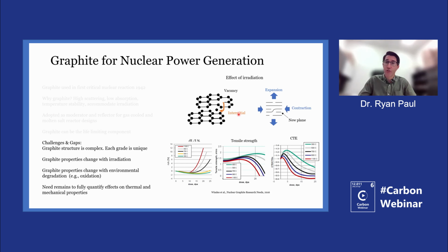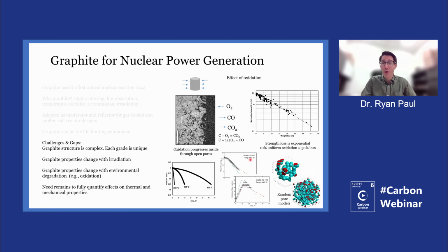So all these changes to the graphite structure result in changes to the volume, changes to the tensile strength, changes to the thermal expansion coefficient, which are very irradiation dose and temperature dependent. And so depending on the design envelope of the reactor particulars, all of these need to be incorporated into the integrity understanding, just from the effect of the irradiation side. And of course, there is potential for other degradation as well. The irradiation degradation will happen over time.